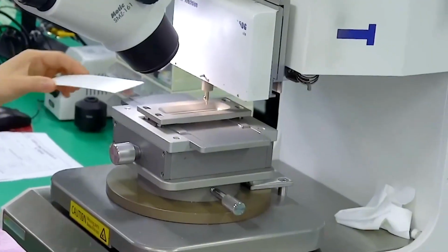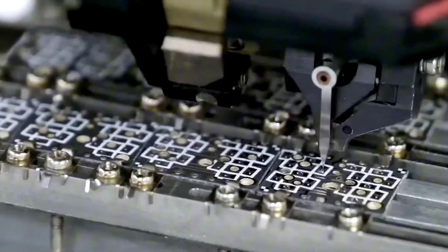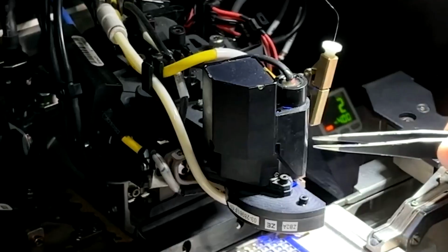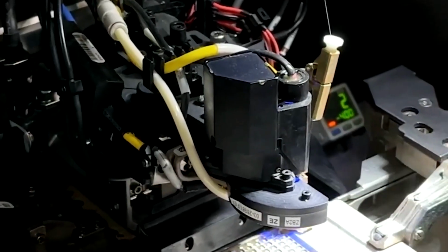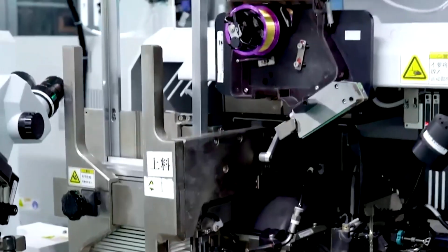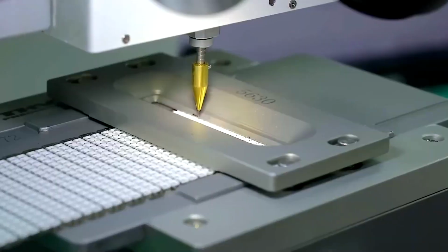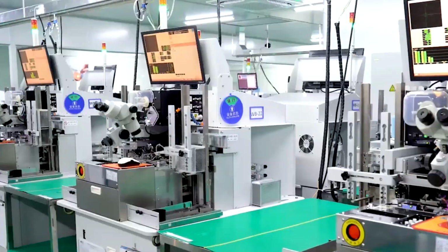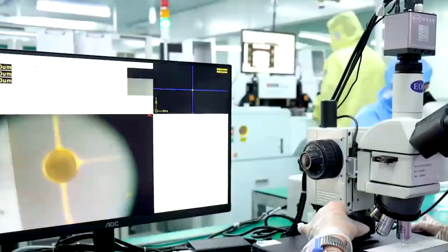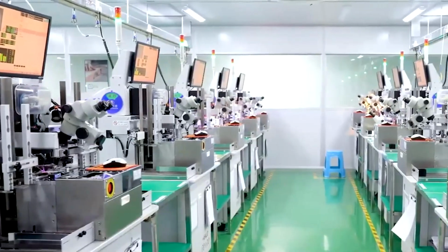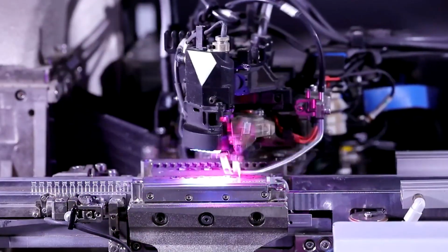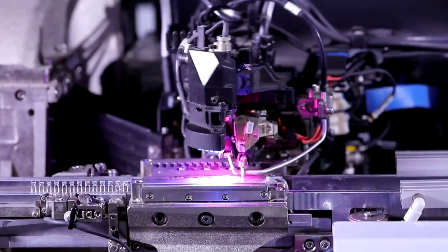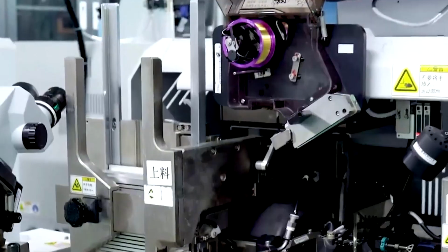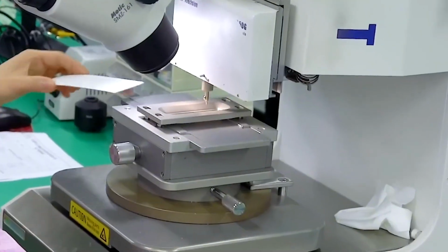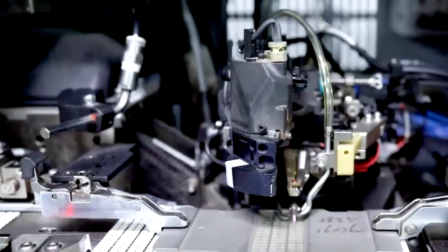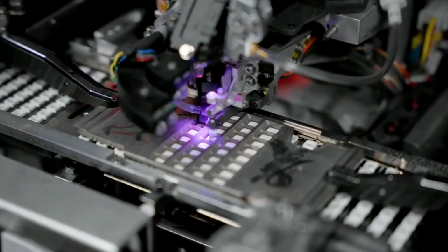It is visible how the machine forms a tiny gold ball at the tip and presses it onto the electrode for the first bond point. The wire is then drawn into a carefully shaped arc before being lowered onto the metal lead. It seems like a simple mechanical movement, but in reality, the second bond requires perfect adhesion. The wire is cut, and the head moves to the next unit without pausing. Despite the extremely high speed, every step maintains uncompromising precision regarding loop height and tensile force. This guarantees a reliable electrical connection and long-term stability for the final product.